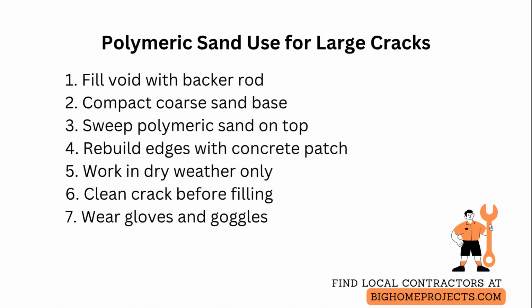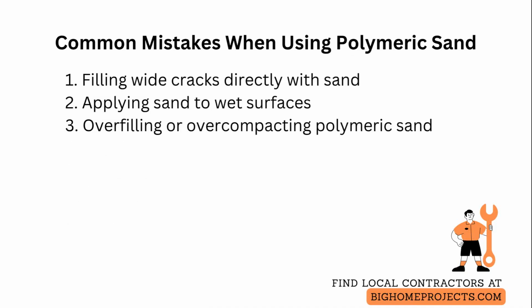Wear gloves and eye protection when handling polymeric sand, and read the product label for specific water application instructions, because too much or too little water will cause weak bonds or washout. The most common mistake is trying to fill a wide or deep crack directly with polymeric sand, which leads to settling and washout. Fix this by first packing the crack with backer rod or compacted sand to the appropriate height, and then adding polymeric sand only at the top.